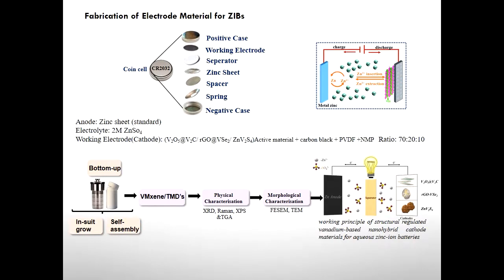Here we will come to the fabrication of the electrode material. The negative case first, then the positive case, working electrode, separator, and then zinc sheet, spacer, spring, and then negative case. Here we use the anode as a zinc sheet and zinc sulfate as an electrolyte, and the working material plus carbon black plus PVDF plus NMP in the ratio of 7:2:1 we will be using for the battery fabrication technique.